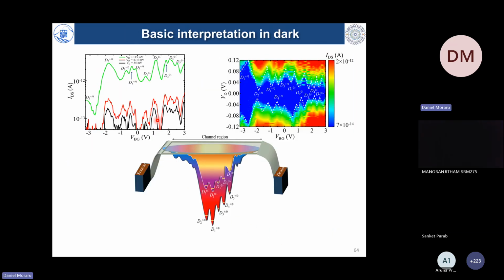How our device is operated is analyzed in this complex slide. We measured many times, and we measured in different ranges. Current peaks can be clearly observed, and these are for different source-drain biases. Stability diagrams with Coulomb diamonds of different shapes can also be observed. This analysis was very difficult because we had to follow very carefully, or as carefully as possible, different Coulomb diamonds and assign them to just a few donors present in the channel. You can see them here counted from D1 to D5, and we've repeated charge states later.